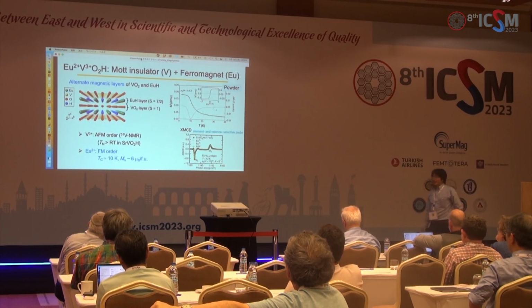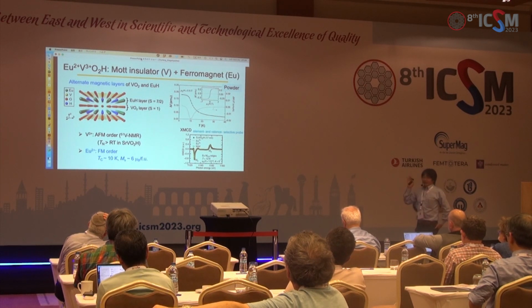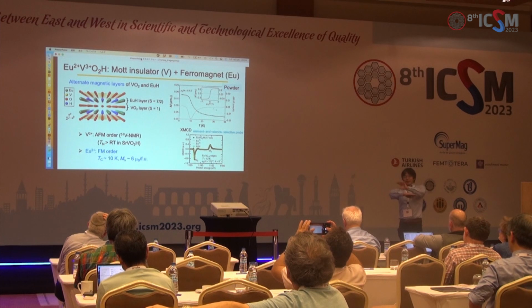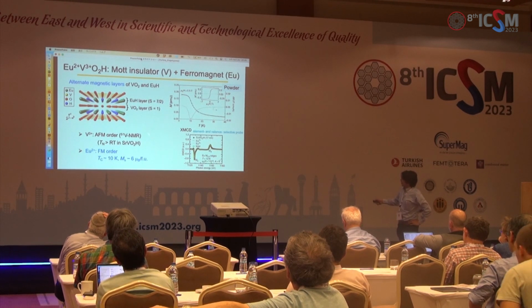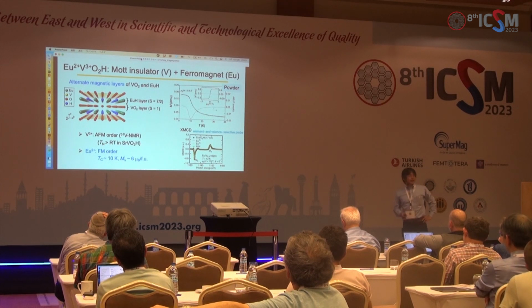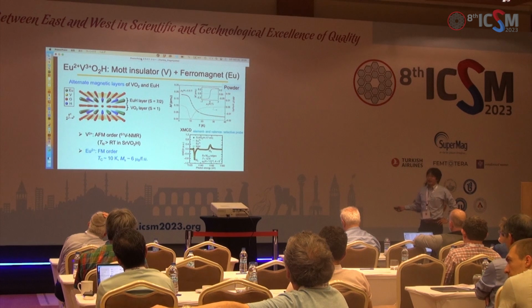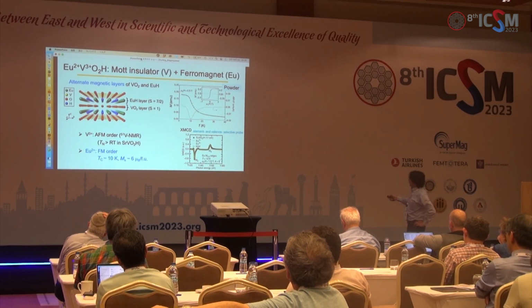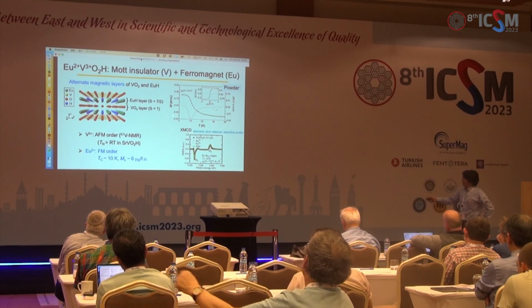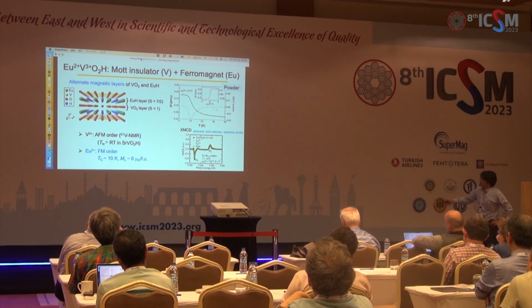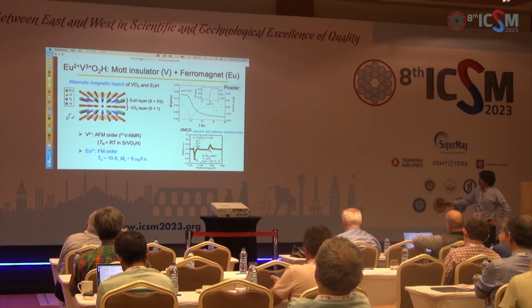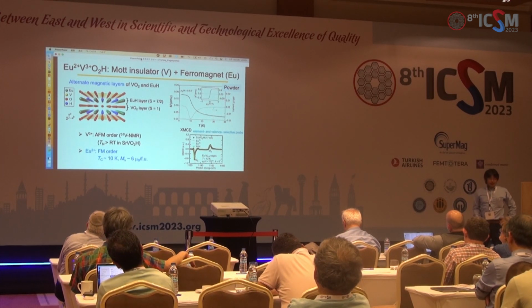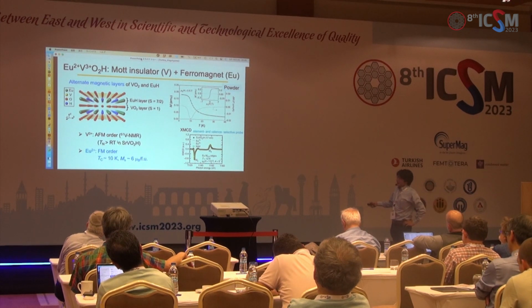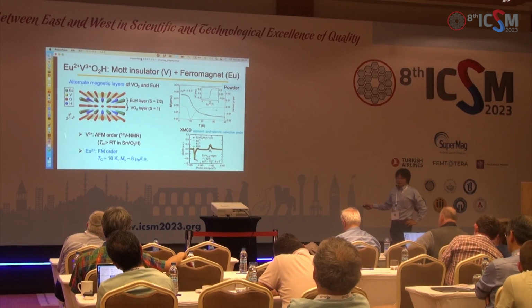Then, from the physics point of view, this material shows an antiferromagnetic state together with the ferromagnetic state. As I mentioned, this vanadium has a two-dimensional layer separated by a hydride ion. So actually, a two-dimensional Mott insulating state is also realized in this material. Actually, we did a vanadium NMR study, and we are nearly sure that this material shows antiferromagnetic order. The ferromagnetic order is actually observed in the temperature dependence of the magnetic susceptibility. You see that the transition temperature is something like 10 Kelvin, and the effective magnetic moment is close to 6 Bohr magnetons. Okay, this supports that EuIIH+ is responsible for ferromagnetism.